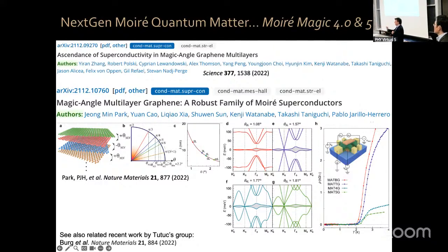That's extremely diluted, orders of magnitude less density of electrons than a regular superconducting metal. However, the TCs are similar to, for example, aluminum, or higher than aluminum, which has 4 orders of magnitude larger electron density. So we do not understand exactly how come the pairing glue of the Cooper pairs in magic angle graphene is so strong.